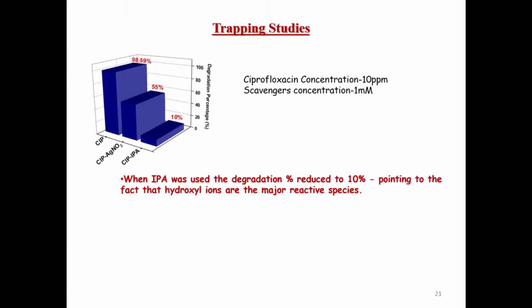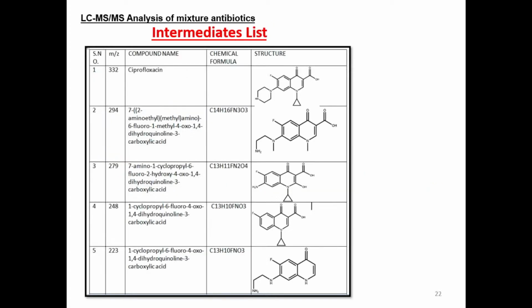Now, the trapping studies, as expected, show a very prominent contribution from hydroxyl radicals, because IPA is one of the scavengers for hydroxyl radicals. You see the degradation is only 10% in the case of IPA. So we can say that the hydroxyl radical is one of the important species taking part. Along with that, you also have a contribution from electrons, where silver nitrate acts as a scavenger. So electrons along with hydroxyl radicals are the species taking important steps in the degradation of these antibiotics.